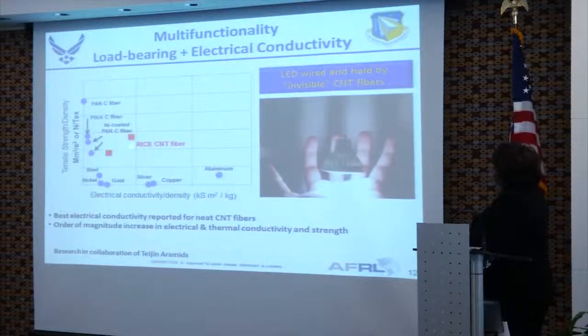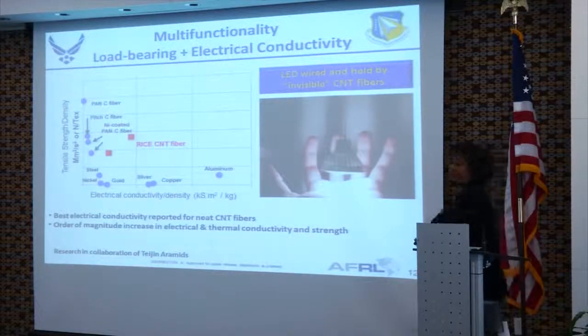If you look at it compared to other typical fibers like polyacrylonitrile fibers and pitch fibers, the conductivity is much higher than these fibers. And there are a lot of applications where you'd like to be able to have this conductivity in a fiber, in a strong, structurally strong fiber. And so in addition to really good electrical conductivity,